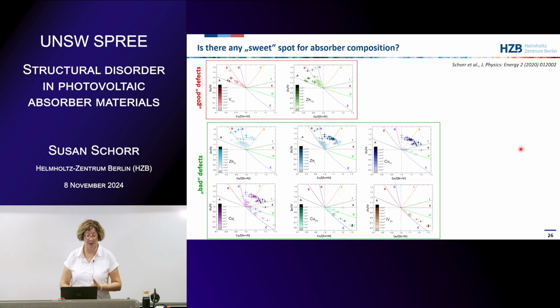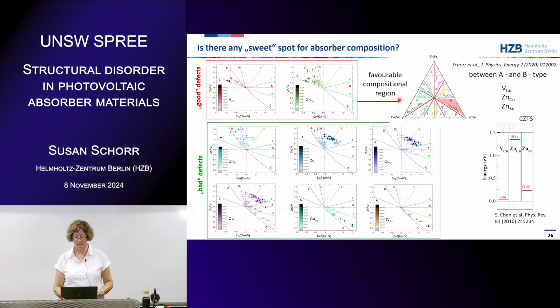So now the question is, is there any sweet spot for the absorber composition? Here in each figure, I made one figure for each point defect, and each point here is a powder sample which was studied. These are all the defects you don't want to have, with the deep levels, the bad defects. And these are copper vacancies and zinc on copper. These are shallow defects. In principle, the favorable region with respect to the point defects is the one between the A and B type line. This is of course copper poor and zinc rich, but also if you are here, you are copper poor and zinc rich. But then you have more of the less favorable defects.